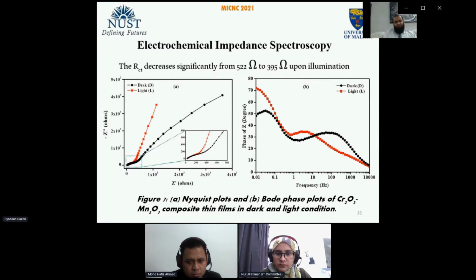At the end, we also supported our photoelectrochemical studies by impedance studies. The impedance studies show that the charge transfer resistance under dark was 522 ohms, which was reduced to 395 ohms upon illumination. This shows that the charge transfer process increases and the resistance of the material decreases because of the maximum electron flow under illumination.